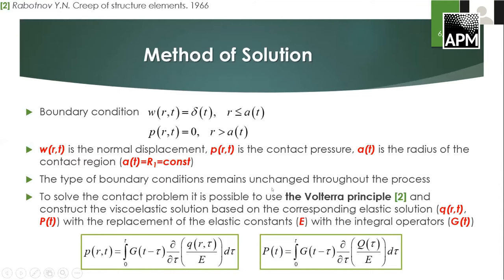Therefore, it is possible to use the Volterra principle. According to this principle, to solve the viscoelastic contact problem, it is necessary to replace the elastic constants of the corresponding elastic problem with integral operators. Thus, for the contact pressure and the applied load, we can write the following expressions where Q is the solution of the elastic problem and G is the relaxation function corresponding to uniaxial tension-compression.